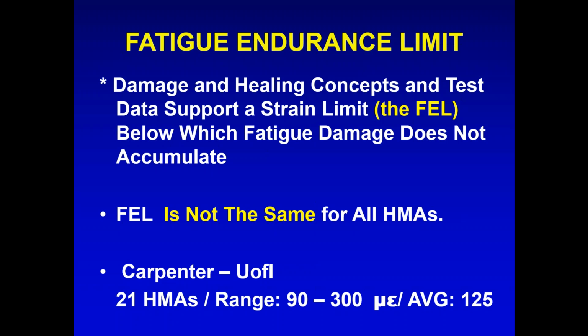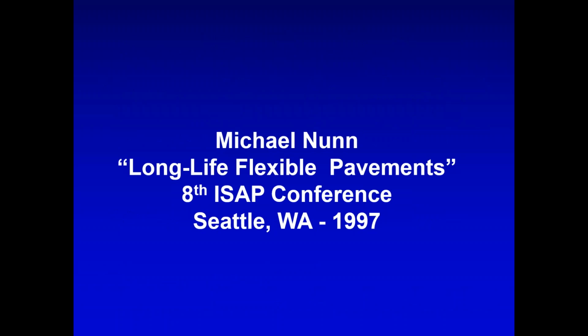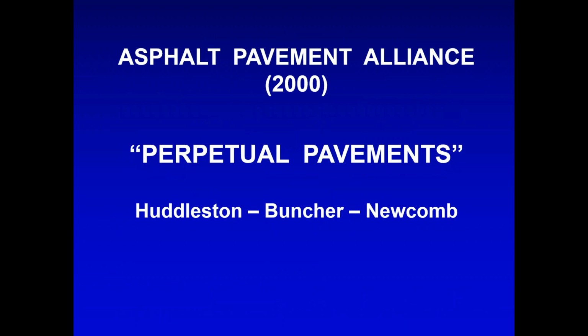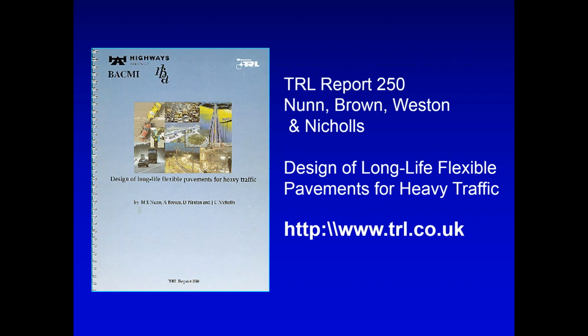It's not the same for all mixes. Sam did a lot of work trying to characterize this. He worked with 21 different mixes. The FEL, fatigue endurance limit, ranged from 90 to 300 microstrain. The average is 125. Mike Nunn in 1997, the UK guy at TRL, first popped up this idea of long life pavements. Then we have the Asphalt Pavement Alliance, basically NAPA and the Asphalt Institute getting together, proposing perpetual pavements that last forever in fatigue, where you just restore the surface.